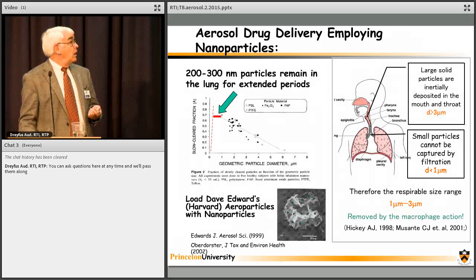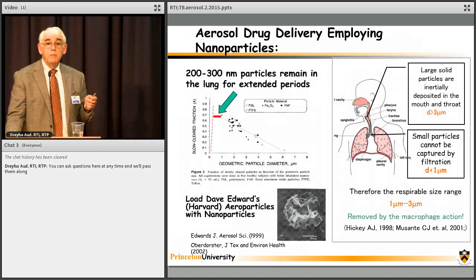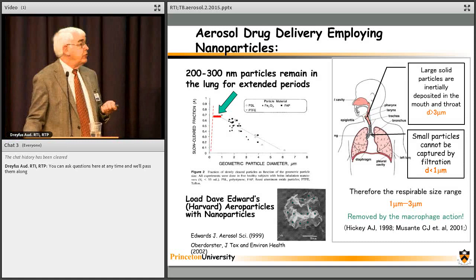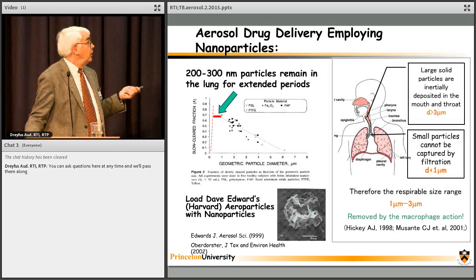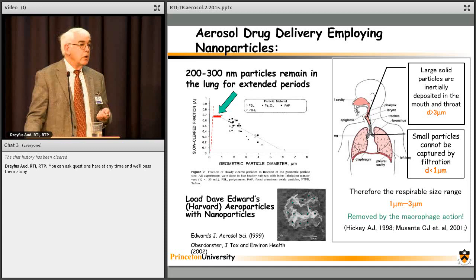And now let's go to the delivery part. So that's the nanoparticles we would want to deliver. And so now this goes back to a slide with Günter Oberdörster, part of this original Gates grant. And the idea here is, this is Günter's data, slow cleared fraction. These are particles that stay in the lungs a long period of time, and this is the particle size. If you make particles too big, they get quickly cleared by macrophages from the lungs. So aerosol, you inhale them, they get cleared.